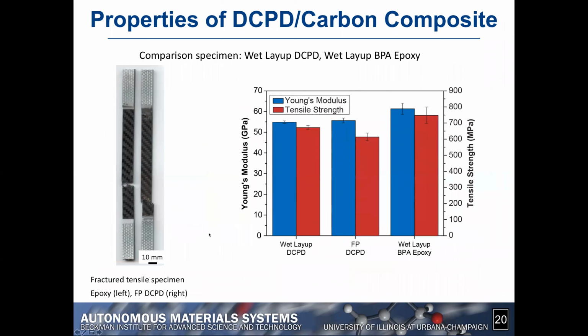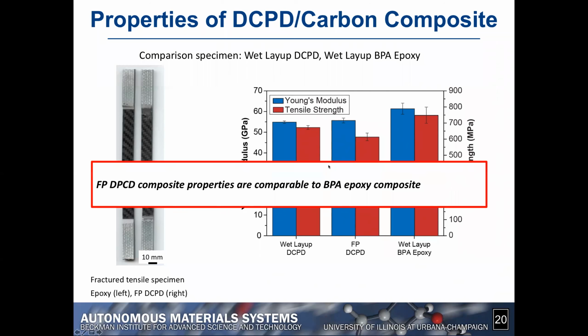Now, looking at the mechanical properties of the DCPD carbon composites, a series of tests were conducted, once again, for the same 3 systems. On the left, you have the Young's modulus and the tensile strength for a composite system made using a conventional bulk polymerization approach. In the middle, the one made through frontal polymerization, and on the right, the reference, which is a carbon epoxy system. And what we observe here is that, once again, the properties are relatively similar. Now, the tensile strength is a bit less than what we would get for an epoxy system, as shown by the red bars over here.